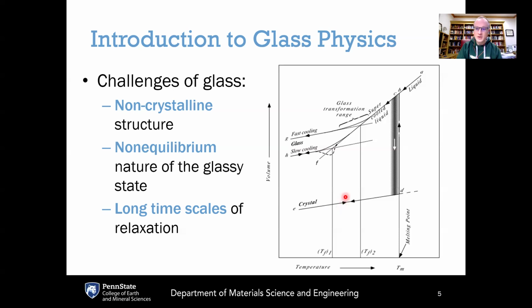Glass is a non-equilibrium material, and in order to get a glass, what we have to do is take this liquid and cool it so fast through this shaded region here where the liquid is likely to crystallize. So we cool it so fast through that crystallization region that the atoms simply don't have enough time to rearrange themselves into a nice crystalline order. And when that happens, you get a phase called the supercooled liquid. A supercooled liquid is any liquid that is cooled below its normal freezing point. From a thermodynamic point of view, this is not the equilibrium phase. The equilibrium would be the crystal.